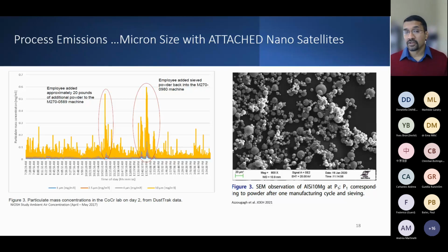The chart on the left actually talks to some of the work that was done in collaboration with NIOSH, where they did particle mass concentration across multiple size fractions. What you see here is with the EOS M270 machines, employees when they were adding powders. I talked about hand charging. At that point, that was the way to do it. And then where they were sieving powder, you see spikes. But this is primarily in the 10 plus micron size range, right? So the larger mass contribution was coming from larger particles.